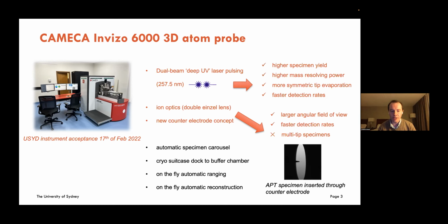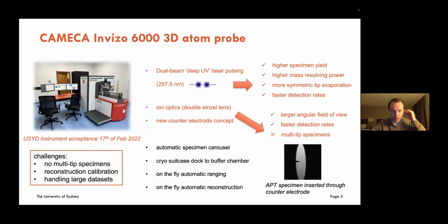There are also some good software improvements when you're running the experiment, such as on-the-fly automatic ranging capability and on-the-fly automatic reconstruction, which for the most part seems to be working quite well. But there are a few challenges that we're trying to mitigate and work through, with no multi-tip specimens, some reconstruction calibration questions, and also some practical implications for handling large data sets. These large data sets we're getting are awesome, of course, but how are we going to curate, store and visualize those? We're going to need increasing computational power as we go from data sets in the tens of millions of atoms well into the hundreds of millions of atoms pretty routinely, and into the billions. So that's something to consider.